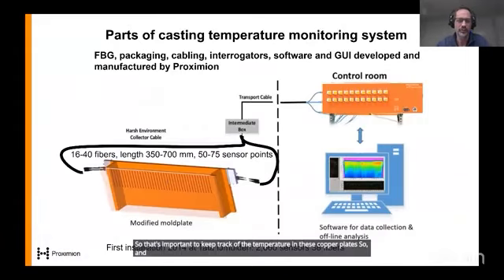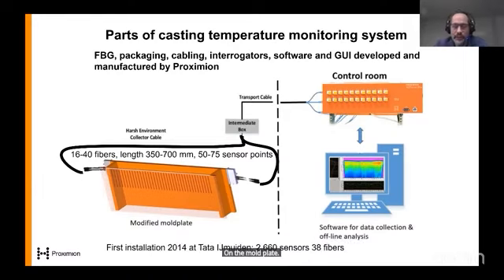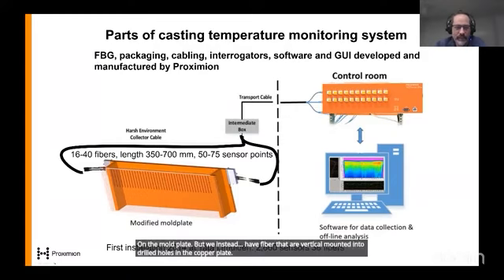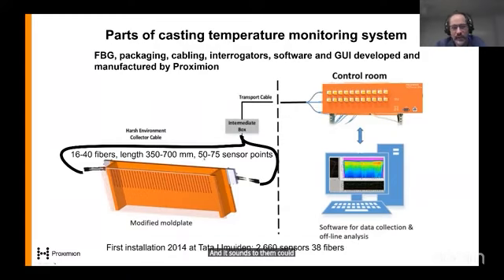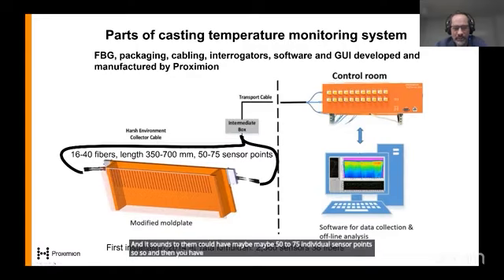You usually do that with thermocouples, but you can have only a very limited number of them, maybe 16 on the mold plate. Instead, we have fibers mounted vertically into drilled holes in the copper plate. Each fiber could have maybe 50 to 75 individual sensor points, and you have this in all the plates in most cases. We did the first installation in 2014.